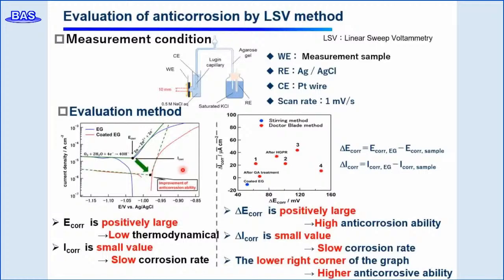The horizontal axis represents the difference in corrosion potential between the bare zinc steel and the covered zinc steel, and the vertical axis represents the difference in corrosion current density between before and after coating the zinc steel. The larger the positive difference in corrosion potential, the better the corrosion protection performance, and the smaller the corrosion current density, the slower the corrosion rate. In other words, the lower right side of the graph shows better corrosion protection.